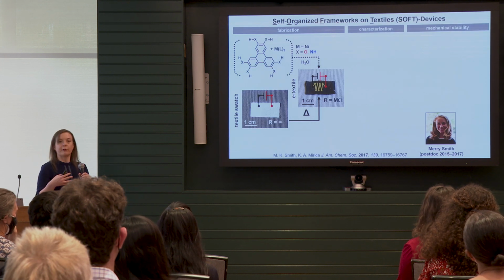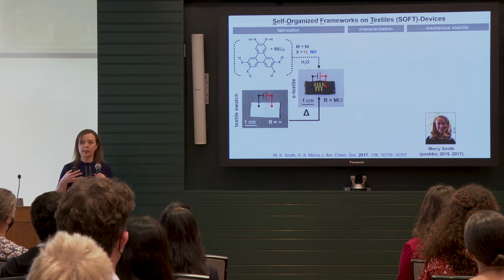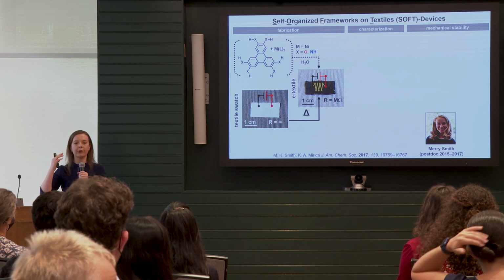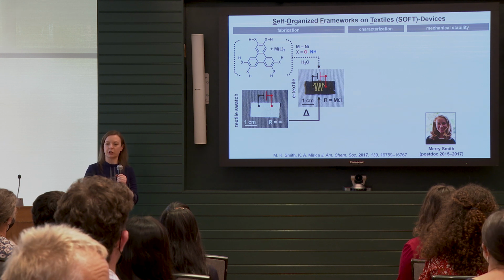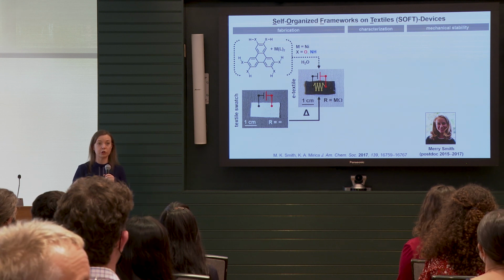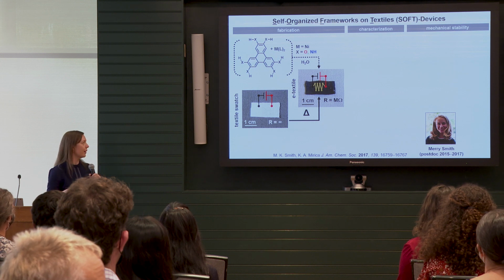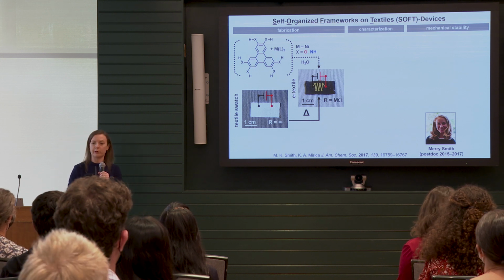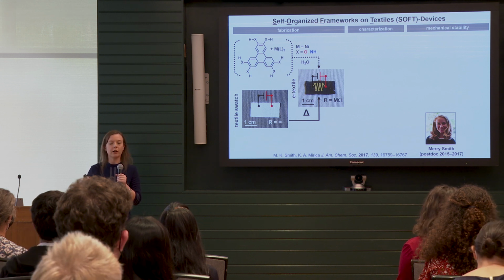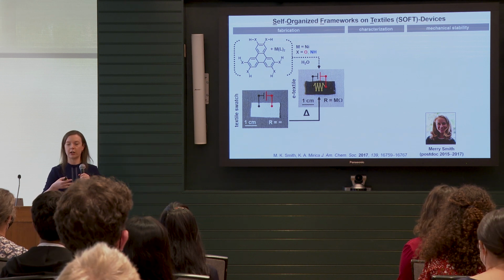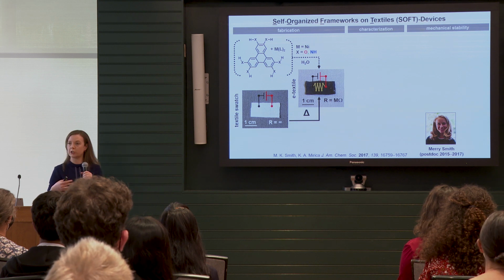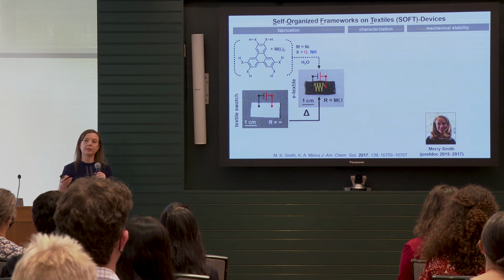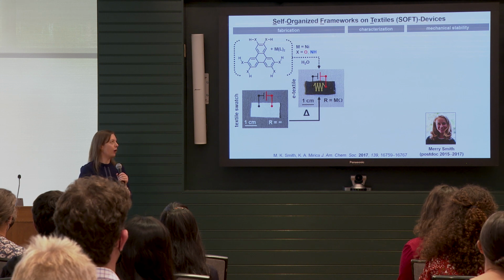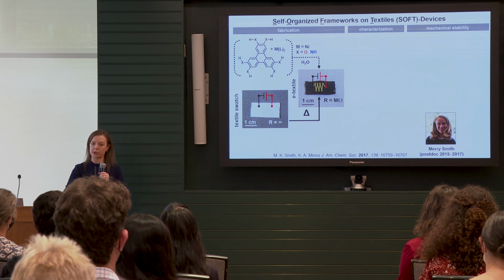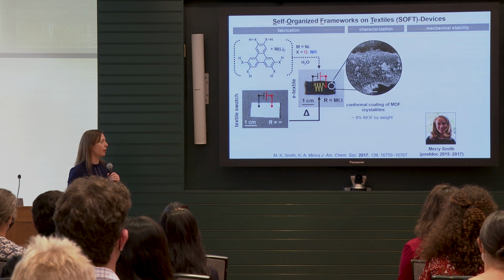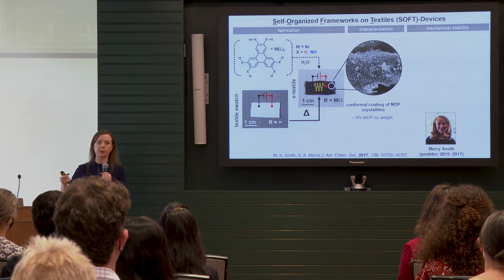Okay. So our focus is to merge this self-assembly process of the material building itself and also combine it with the integration step onto a textile substrate to achieve a textile-based chemical sensor. In this particular example, what I'm showing is that we can take a cotton swatch and simply run the reaction in the presence of the cotton substrate under similar conditions to what I've shown, and get templated assembly of this material onto the cotton substrate